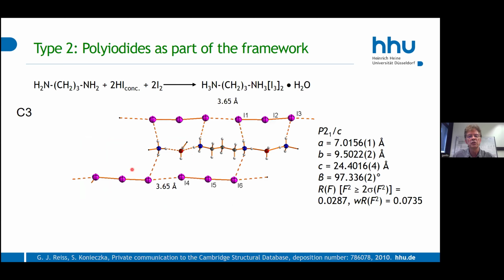So let's go further. We also tried a really short chained tecton in this case. And this is so short that it really doesn't work with I3-, but always in hydroiodic acid, we have a lot of water. And in this case, simply the water molecules are added as part of the tecton. So we understand the cation plus the water as this primary tecton, which produces our polyiodide. Also here we got these I3- one-dimensional chains. And the fun fact is that these chains run along the b direction, and especially from this iodine position to the next iodine position is exactly the lattice constant. So sometimes you just see the structure already in the unit cell.